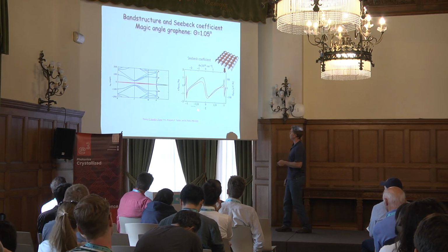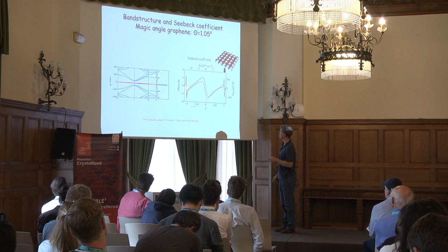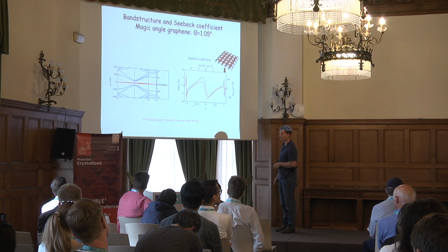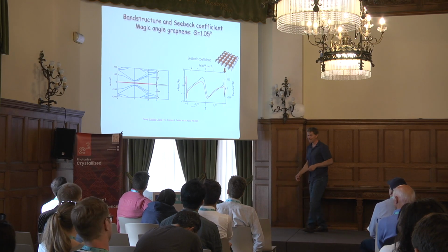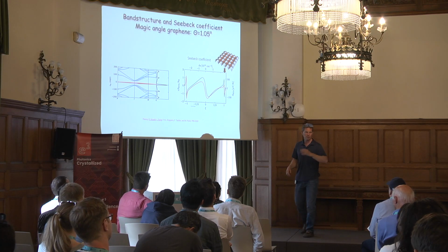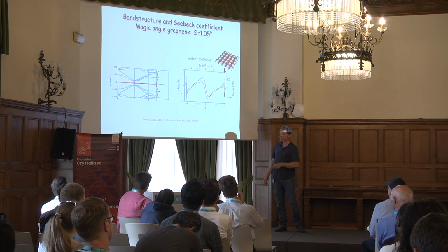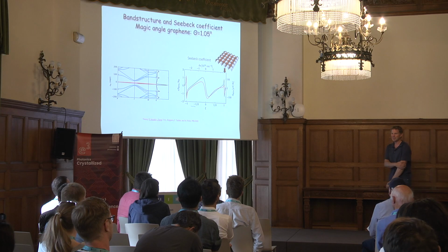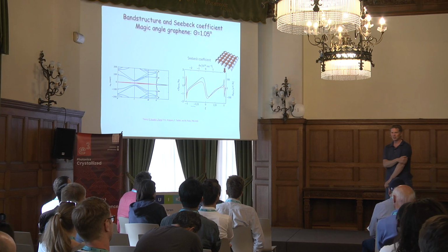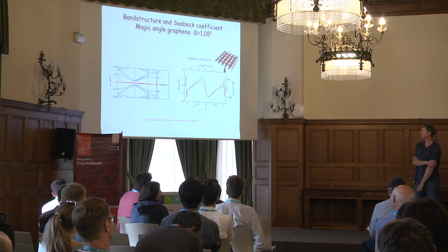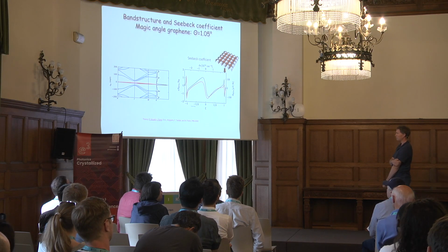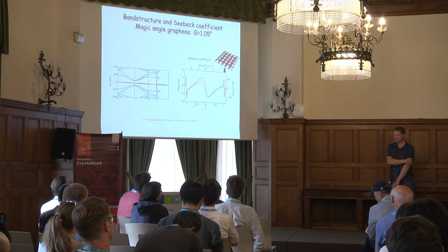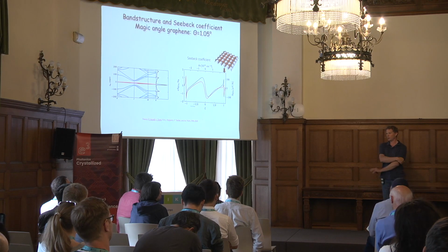So you don't see, for example, these filling peaks anymore, right? It's completely smeared out. So any paper that claims to see effects of quarter filling and three-quarter filling in twisted graphene at room temperature, that is complete nonsense, okay? And there was a paper in Nature that was actually claiming that. That's just not possible at room temperature, and that's really basic physics. The flat bands are that flat. That's apart from correlated states, right? That's just filling the bands. Of course, for correlated states, you usually need lower temperature.